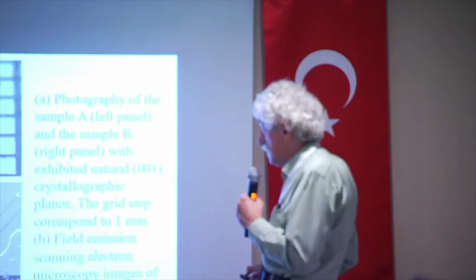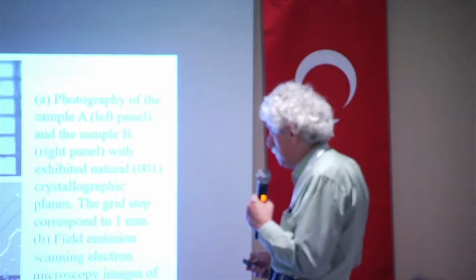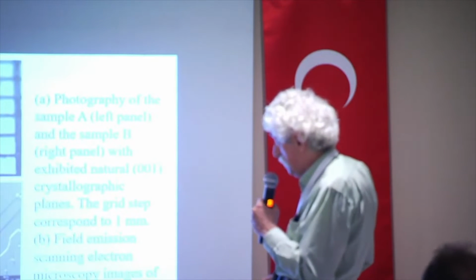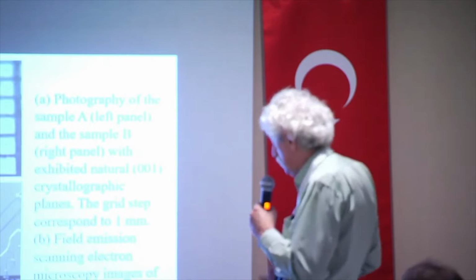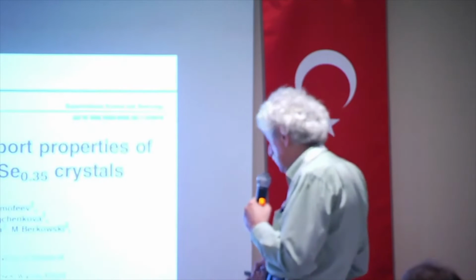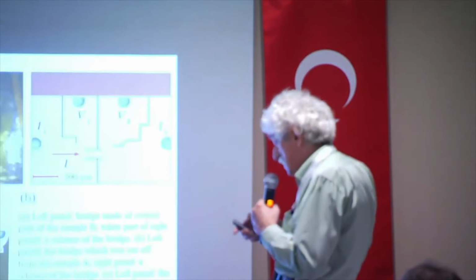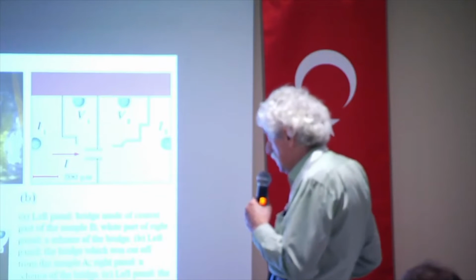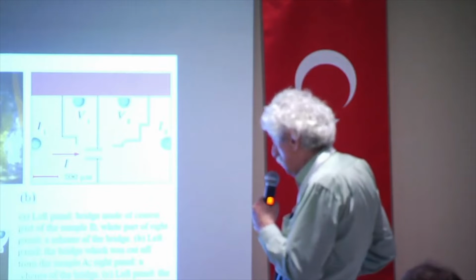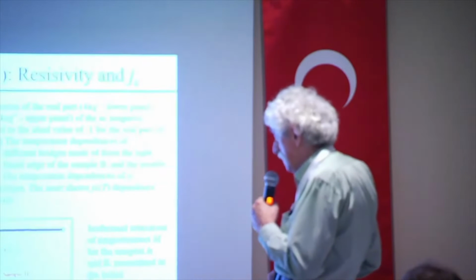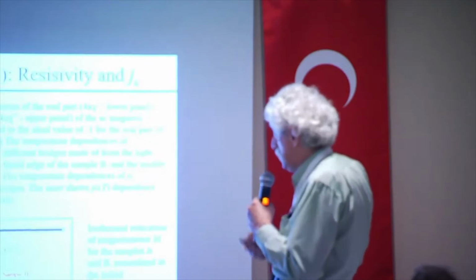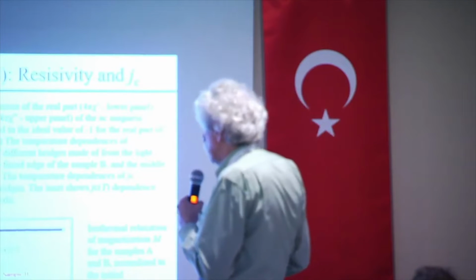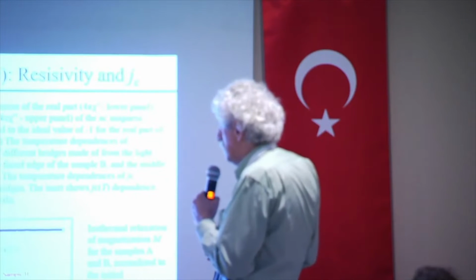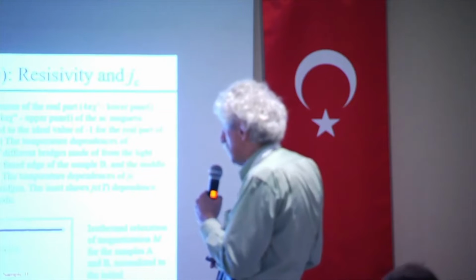And so we decided to perform transport measurements for such materials. This is a crystal which is grown very fast. This is a crystal which is grown very slowly. This is millimetric paper. You can see the difference. If you make an extension of this picture, you can see here. The paper was published a few years ago. And by making bridges, we put current, and we found again this crystal, which was grown with very high speed, very fast, and this crystal which is grown very slow.